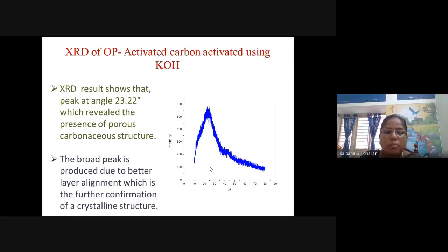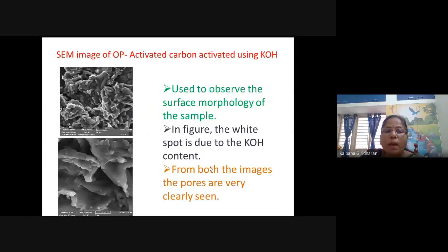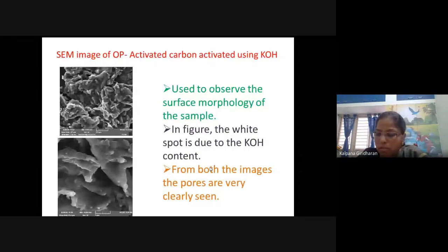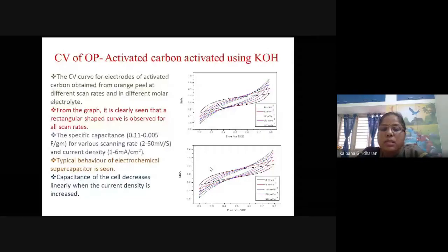This is a typical carbon peak we found, and this is the corresponding image. We observed the surface morphology is very uniform. There is a bit of KOH in it, but we washed it properly so the KOH is completely removed. This is the CV of activated carbon from orange peel.